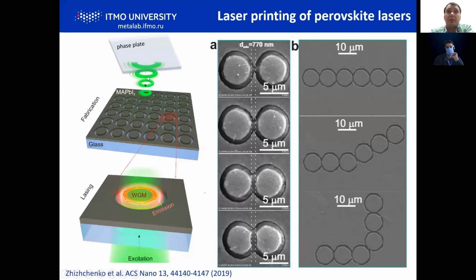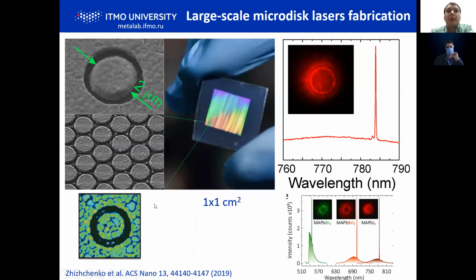It means that we can apply femtosecond laser pulses shaped by phase plates, for instance. In this case we deposit a perovskite film on glass, apply donut-like laser pulses and cut micro disks. We can cut different designs, and each micro disk can support a whispering gallery mode, and after excitation it initiates laser emission. In our work, we create either single micro disks or a huge array of perovskite micro disks, a billion of micro disks, which can be created in less than half an hour.